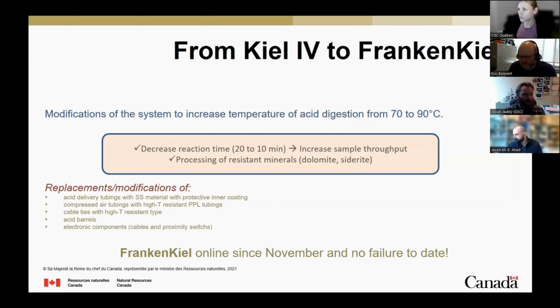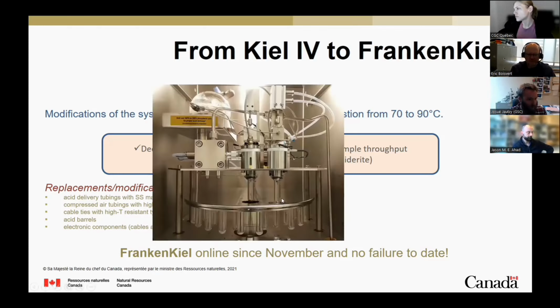This washer and dryer kind of thing you saw is called a Kiel IV, and we modified it, so we rebaptized it Frankenkiel. Basically, all the modifications we've made are plumbing modifications, remachining some pieces and stuff like that. And that allows us to go from an acid digestion temperature of those carbonates from 70 to 90 degrees Celsius. Actually, we could go higher. We can go up to 120, but we have tested it up to 90 right now. The consequence is that we can decrease the reaction time down to 10 minutes, so high sample throughput, but also, which is very important, we can attack more resistant minerals, such as dolomite in our case here, but we are planning on doing siderite, which could be very interesting for other systems.